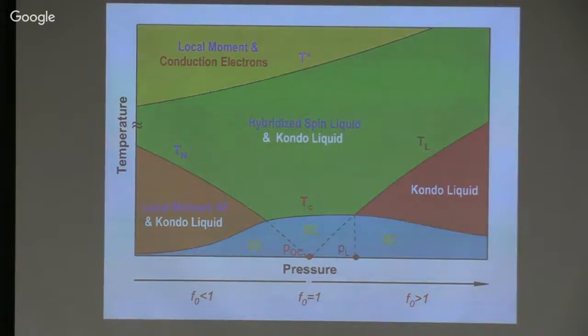But the other really interesting feature is there's a line there called TL. What is that? That's the line below which you have only itinerant electrons. Because F0 is greater than 1, it's easy to see, but then you can get F equal 1 at a finite temperature. And that line TL marks then the boundary between localized and itinerant behavior. Above it, you're always going to have some local moments. Below it, you only have itinerant behavior.